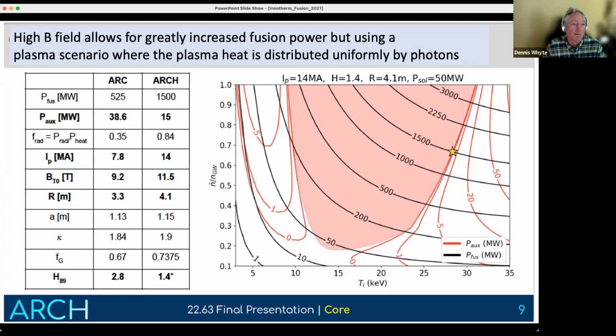So it has almost infinite energy gain on it. And that's actually this line that's going up along here. You'll notice, by the way, that there are actually points along this contour that are at higher fusion power, up at 3,000 megawatts, but we couldn't use it, even though it's physically accessible, because we had no heat exhaust solution for it at that point.